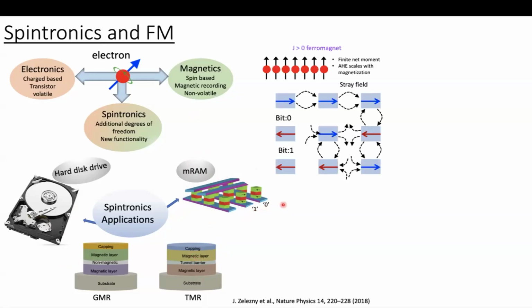So till today, we broadly use ferromagnet for these spintronic devices. The main reason is that in ferromagnet, there is a finite net moment, and it's easy to manipulate the magnetization or domain structure by external magnetic field and or external current. And the writing or reading speed in this class of material is typically in the gigahertz range. But because of this finite net moment, there will always be a finite stray field, and that limits the data density in a device.